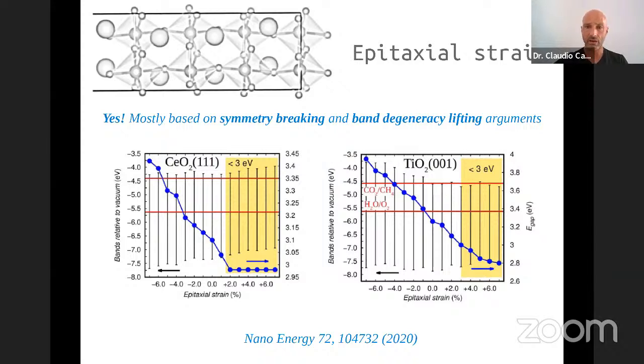In fact, many of these effects, for both the cerium dioxide and titanium dioxide, can be understood in terms of symmetry breaking of the structure, right? That gives rise to band structure degeneracy lifting. So essentially at 0 strain, some of the energy bands are degenerate at the top of the valence band and the bottom of the conduction band. But when you introduce this strain, the symmetry is lower, and as a result, the degeneracy is broken, lifted. And as a result of that, you can get a smaller energy band gap, right?